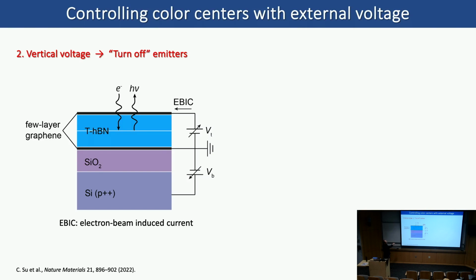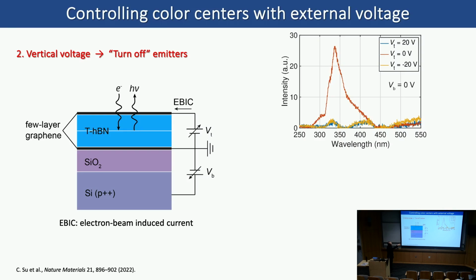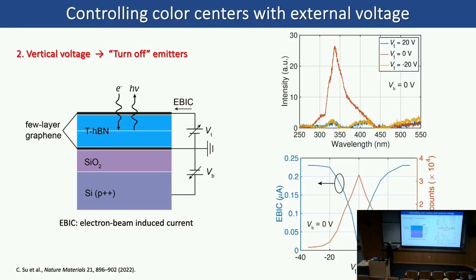This is just by adding 2 electrodes encapsulating the twisted hBN feature, with a vertical voltage. And this is the peak that originally was emitted by that 4eV emitter. But once you add a vertical voltage, most of the emission got quenched. So it becomes pretty dark. And if you look at what is called the electron beam induced current, EBIC, which is the current going through this circuit whenever there is an E-beam excitation, it has an anti-correlation with the UV photon counts. So whenever you have a higher EBIC, you get a lower UV photon count. Which means that the excitons, which used to recombine and produce those UV photons, become a current. So we proved that these 2 things have the same origin, which is the band edge exciton.